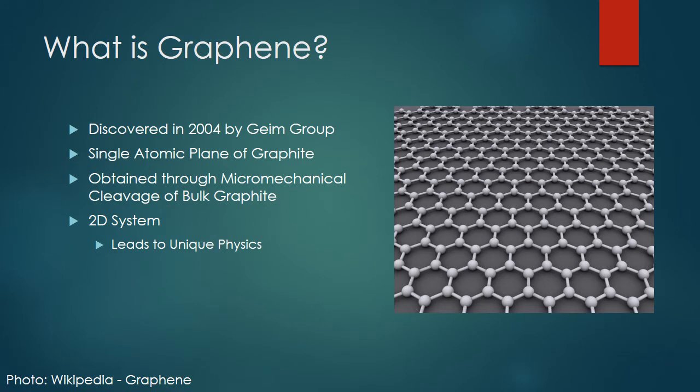So what exactly is graphene? Graphene is the first truly two-dimensional condensed matter system discovered experimentally by the Geim Group at the University of Manchester in 2004. It is a single atom thick honeycomb lattice of carbon atoms. One of the more popular ways to create graphene flakes is through micromechanical cleavage of bulk graphite, which on the surface looks nothing more than just scribbling a dark patch with a pencil and using sticky tape to remove a layer, then searching for maybe a 1 micron-sized flake of graphene amidst a centimeter-sized square of graphite. While pencil lead seems unexciting, the discovery of this 2D system introduced some surprising new physics and potential, which led to its current popularity today.